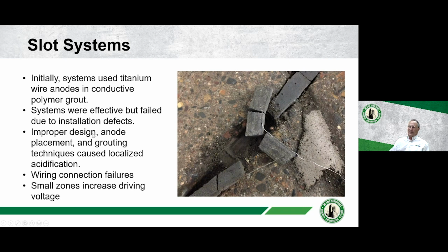They also found that if it's improperly designed or installed, you can have some real issues. If you run it too hot, you get the same thing with acidification along the anodes. If you have a short circuit, or there's a really close reinforcement bar near one of these slots, it'll dump current, and when it dumps current, it will acidify. So this acidification is the biggest problem that they had with these initial slot systems. And they came up with a current density that will pretty much eliminate that acidification problem in current practice.